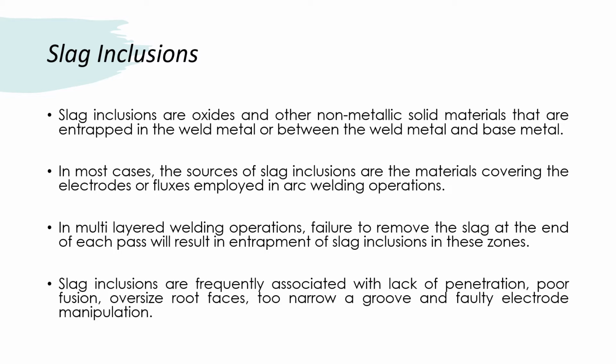In multi-layer welding operations, failure to remove the slag at the end of each pass will result in entrapment of slag inclusions in this zone. Slag inclusions are frequently associated with lack of penetration, poor fusion, oversized root faces, too narrow a groove, and faulty electrode manipulation.